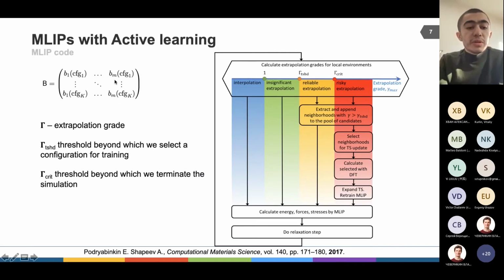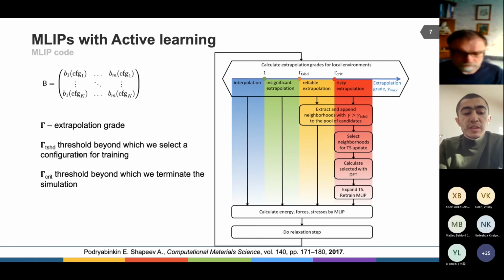In the active learning technique, we have to provide some parameter which is called the extrapolation grade, and it can be mathematically shown that the moment tensor potential extrapolates if this parameter is more than one, and interpolates otherwise. In practical simulations with the machine learning interatomic potential code, we use the so-called two-threshold scheme, which is illustrated here. In this scheme, we choose two thresholds. The first threshold is the one beyond which we select a configuration for training, and the second threshold is the one beyond which we terminate the simulation.